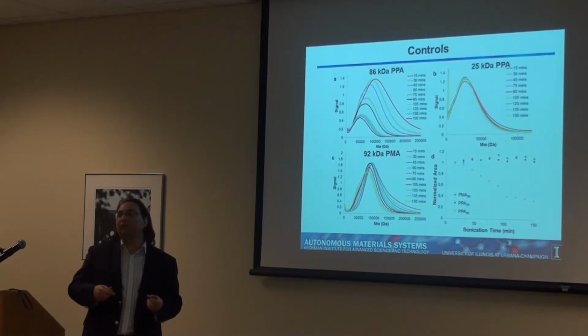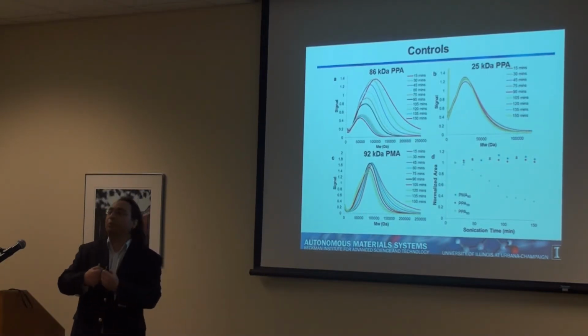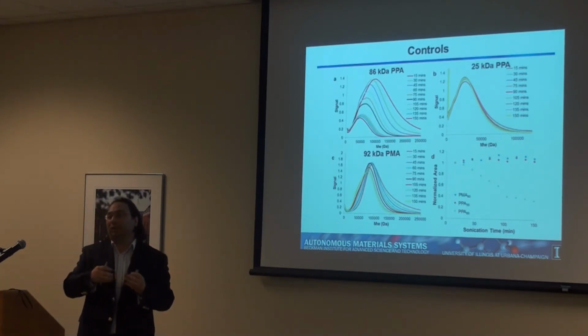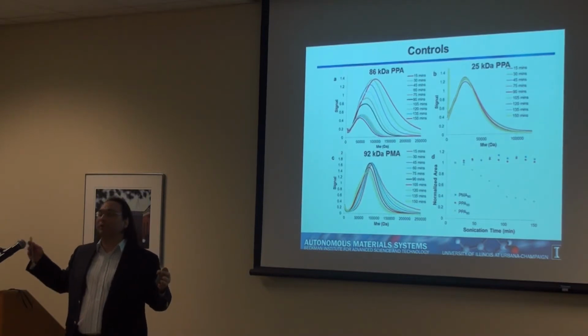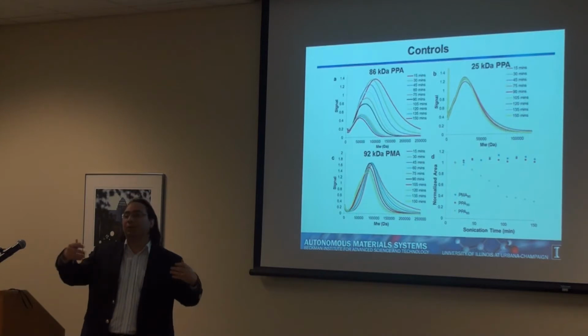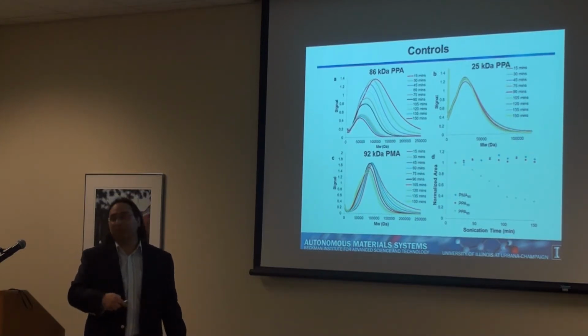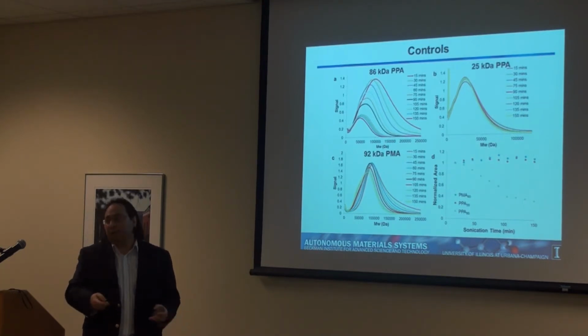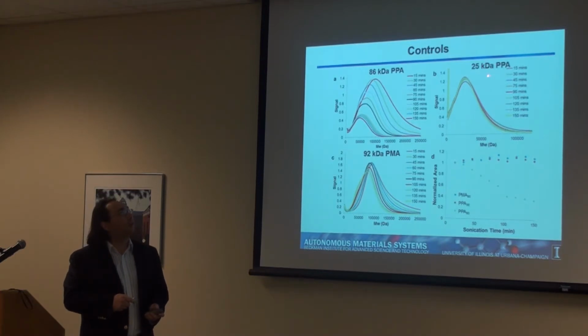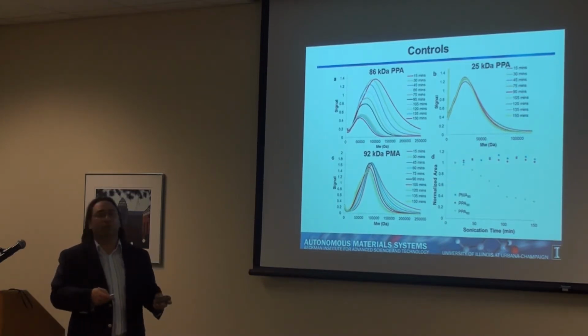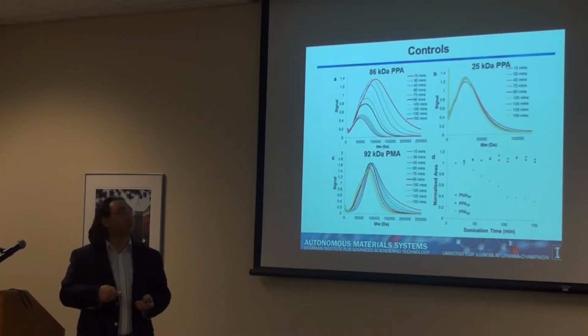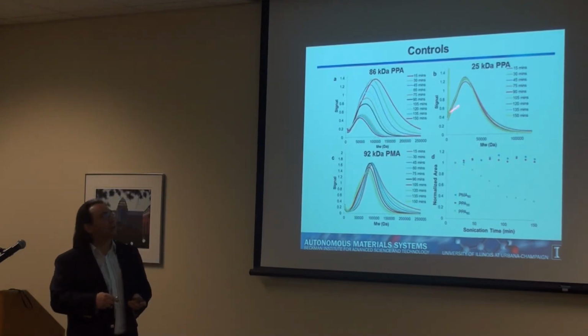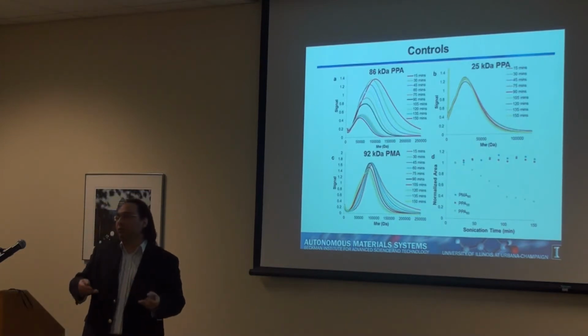Also, one thing that I didn't say before is that in order for this mechanical force to be enough to break a carbon-oxygen bond in this case, the polymer needs to be at least a certain size. If the polymer is too small, then you cannot pass enough force to break a chemical bond. So this gives us a different control, which is just taking the same polymer and using a much smaller one. In this case, you have a 25 kilodalton PPA, the same polymer, the same chemical structure, just smaller. And when you apply ultrasonication to that, no changes are observed. So just to summarize, you can integrate all these areas, and you see that the area doesn't change for the two controls, but it goes down with time for the PPA case, though not to zero, because again, what remains is too small to break in the middle.